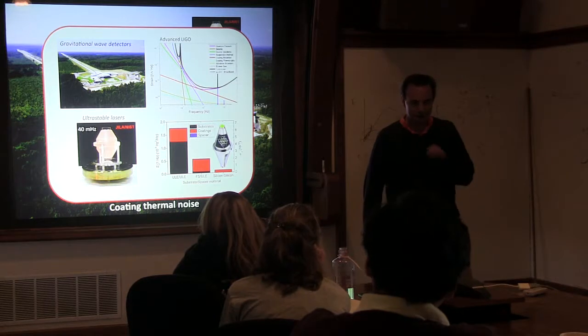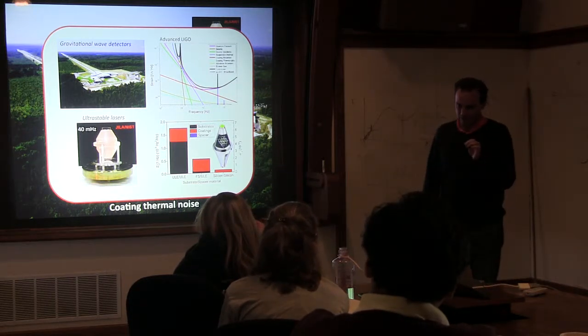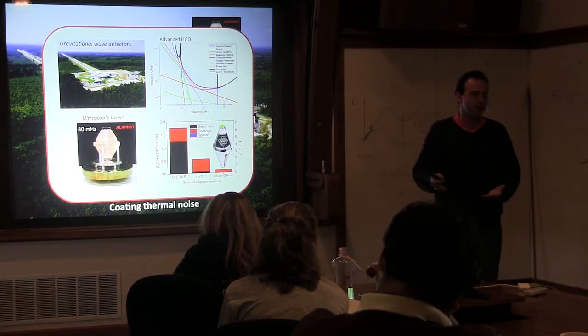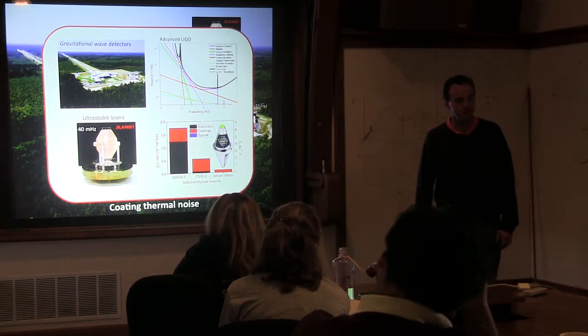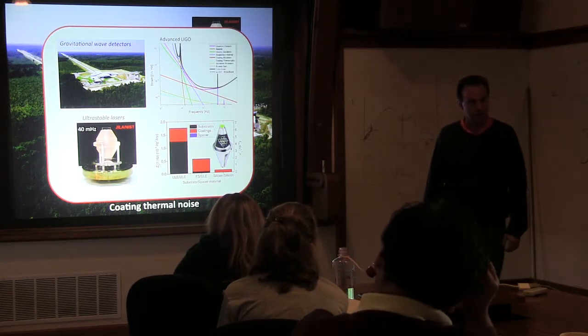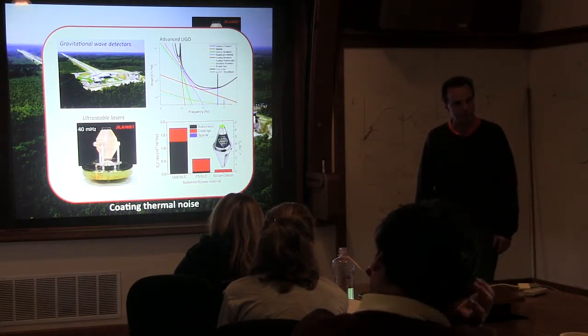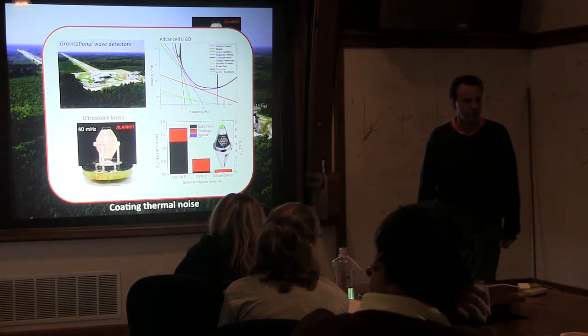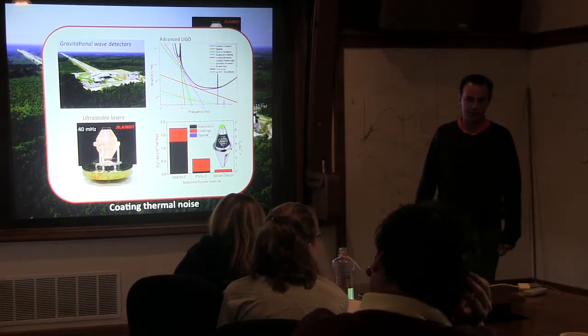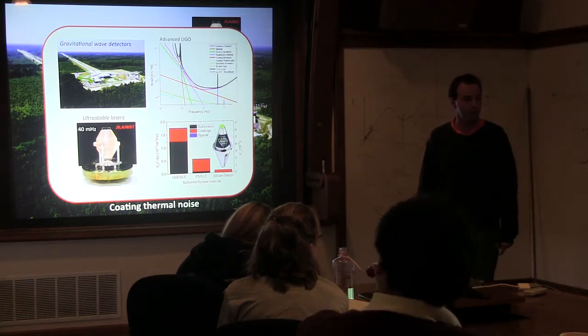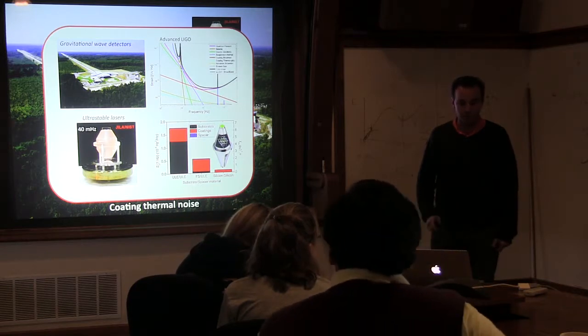The solution is really ultra high purity MBE. You can have MBE growth with very few impurity atoms that basically minimize the absorption. And we are now almost at the same level as the silica tantalum coatings, which we also wouldn't have thought possible.